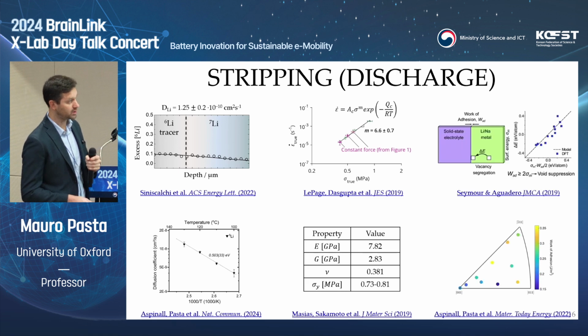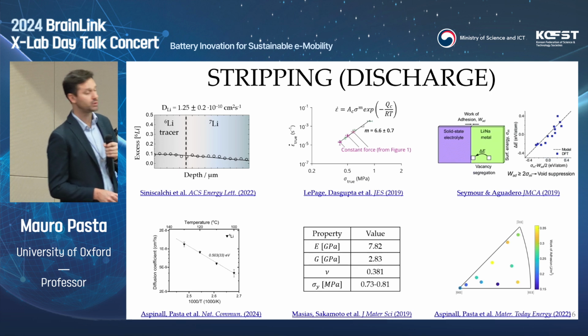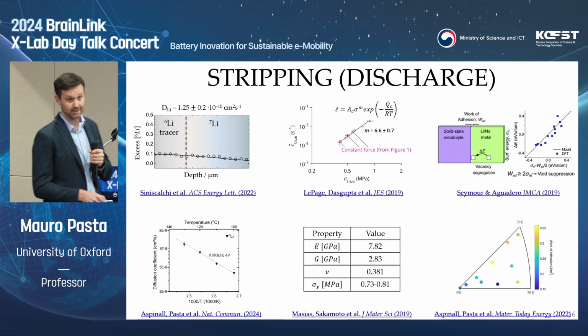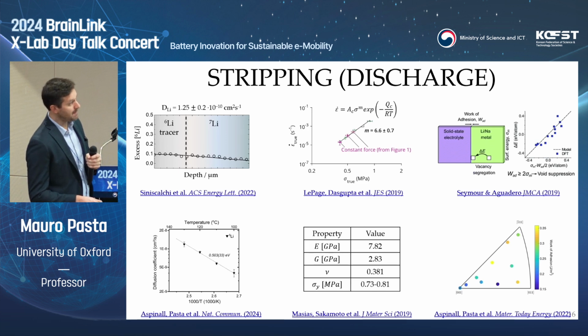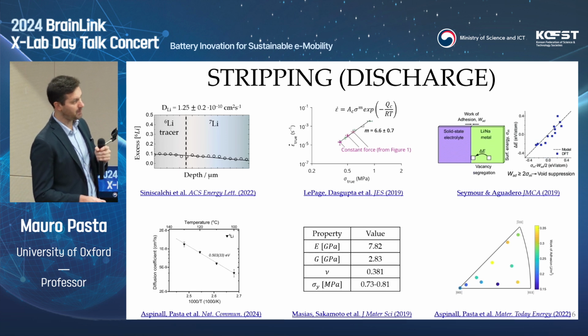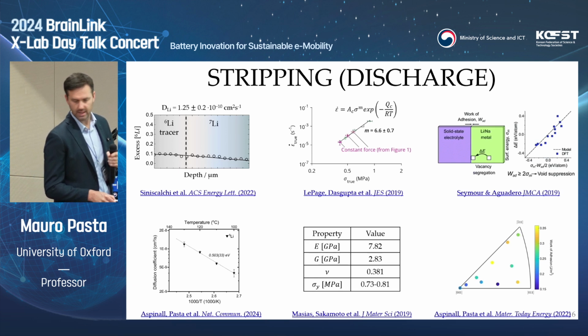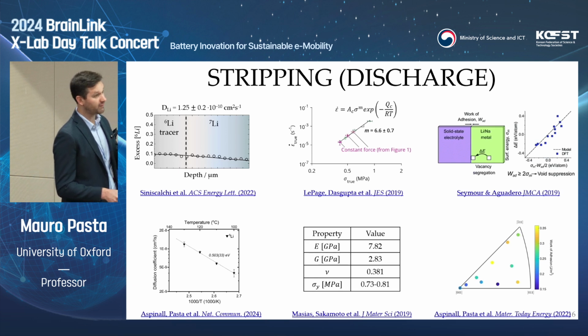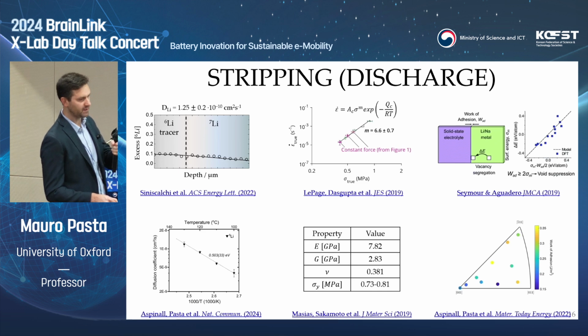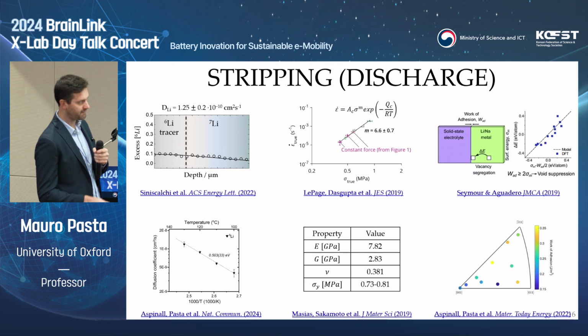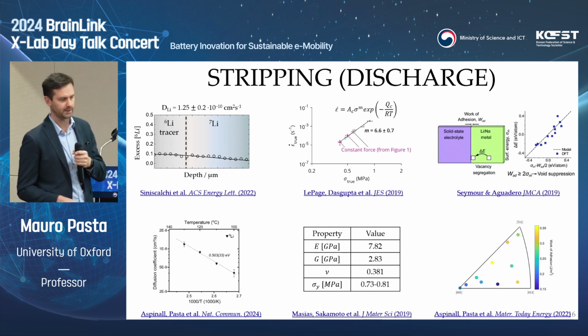The other thing that is important to note is the interface, and in particular the interfacial properties between metallic lithium and your solid electrolyte, in particular the work of adhesion. If you remember what I mentioned earlier, in an idealized system, you need to create a vacancy to start with to then generate a void. So if the work of adhesion is higher, it becomes more difficult to create that vacancy and therefore to coalesce and form voids. So interfacial properties are also extremely important.